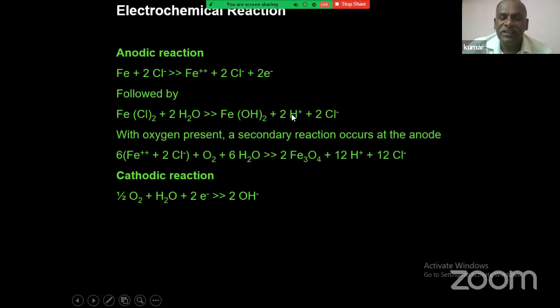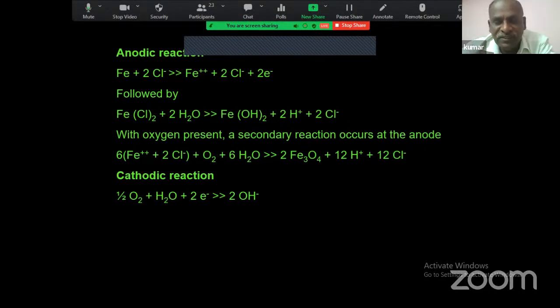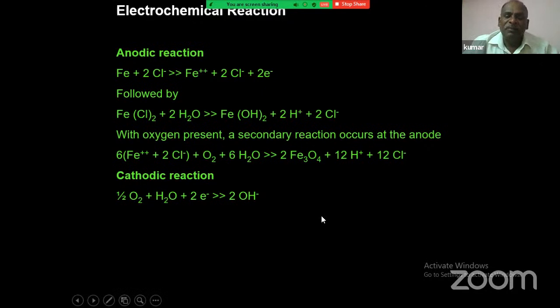And hydrogen is evolving, 2H plus is there, and 2Cl minus is there. Then what will happen? It forms HCl. HCl is the acid. So the Cl minus initially disrupts the passive film and initiates the corrosion. Then after that it dissociates and creates a reduction in pH. That means it creates an acidic environment. So you know very well that when it is acidic, as per the potential-pH diagram, the corrosion will be much faster. So through this, what we can understand is that when the chloride is contaminating, the corrosion is very, very dangerous for the structure, especially for the steel in concrete structure. So we have to avoid chloride penetrating into the concrete.